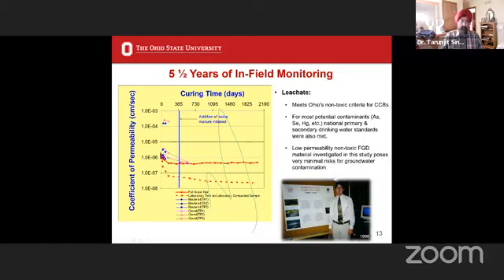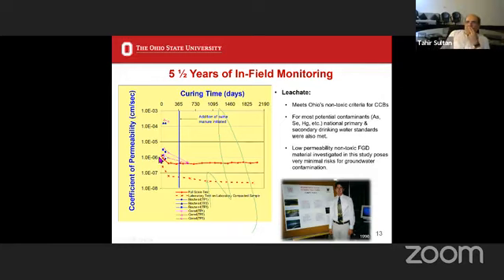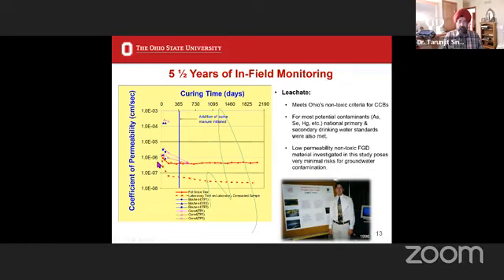So if you want 10^-6 in the field, you would want 10^-7 per second in the lab. And what we found, the same thing worked for us for FGD materials. So our recommendation is that one does not need to measure the permeability in the full scale field. Whatever you want the performance criteria in the lab, achieve a permeability value that is an order of magnitude lower. See, minus seven is lower than minus six, and that will suffice.